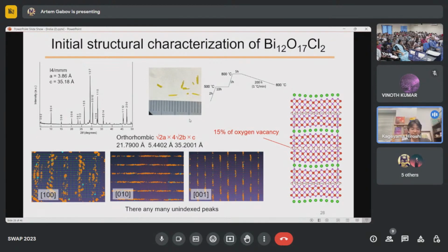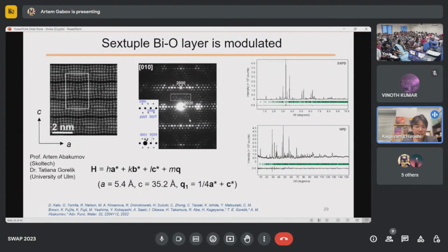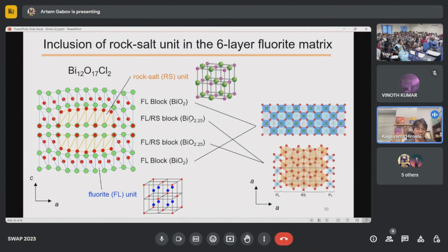Actually, this cannot be indexed by using simple superstructures. Okay. Then once again, we collaborated with Artem Abakumov, who uses the TEM, and he observed this wavy behavior in the crystal structure. Then by using this incommensurate type of modulation, he was able to solve the crystal structure. Okay. Then we found this is the final crystal structure.